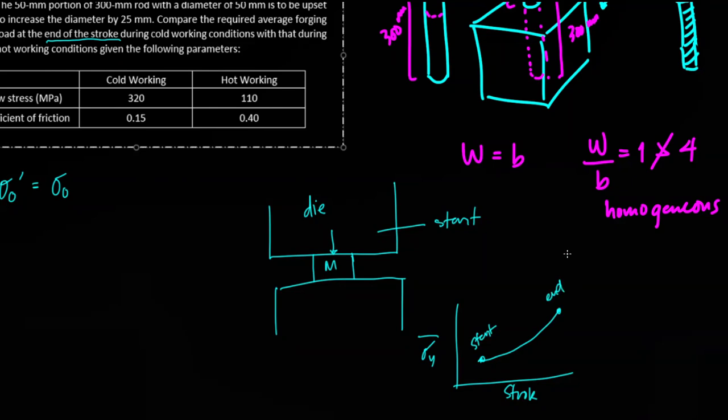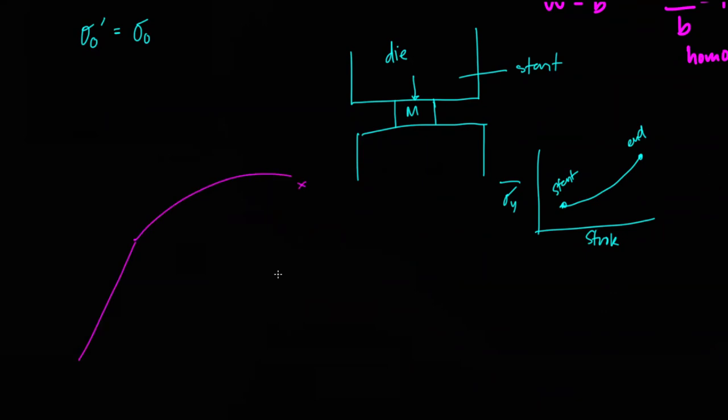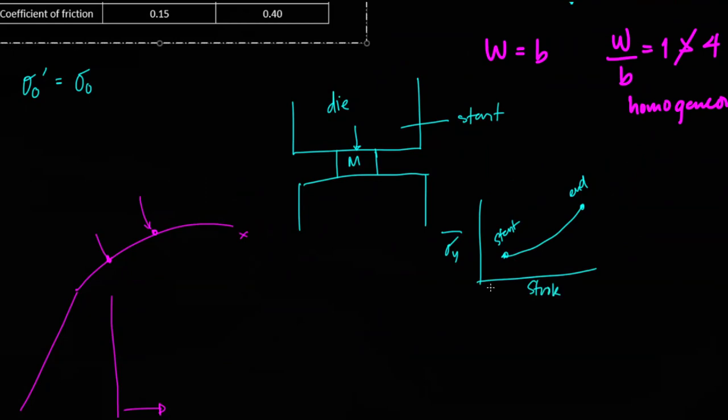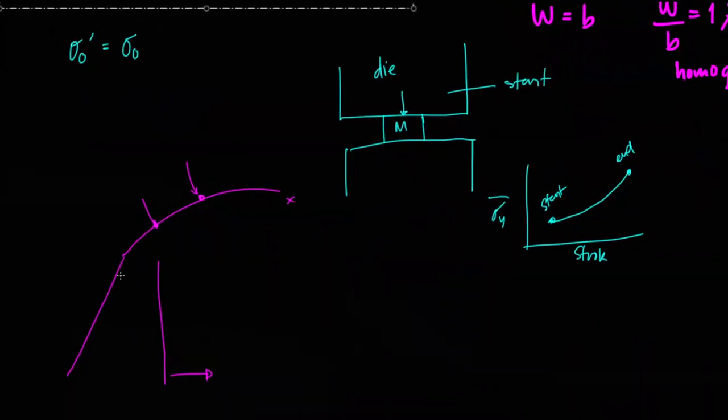So why is this so, no? So we remember that, diba, the flow stress is, and we go back to the discussion, sana naalala niyo pa, no? So parang sinabi ko dati, if this is the stress strain diagram, no, the flow stress is actually the instantaneous stress that is required to continuously deform your metal, no? So it makes sense because pagka you're continuously deforming your metal, nagko-continuously nag-introduce ka ng strain hardening effects. So it makes sense na kunwari from this deformation, if you proceed further, then it requires actually a higher stress value, no, or higher flow stress. So actually within this forging stroke cycle, yung sigma prime, which is your flow stress, is actually also increasing, no? Para nag-i-increase siya as you introduce more and more deformation.